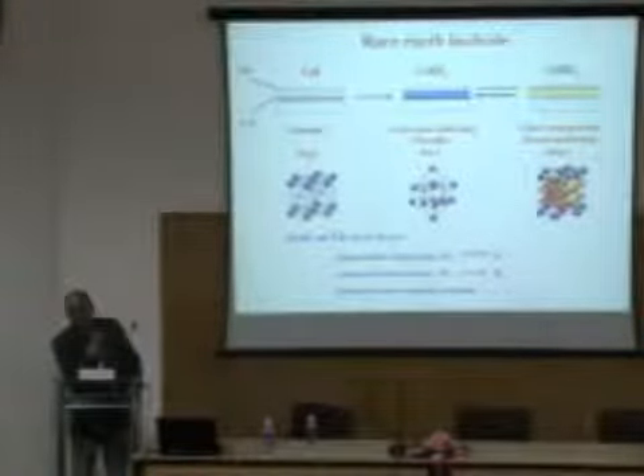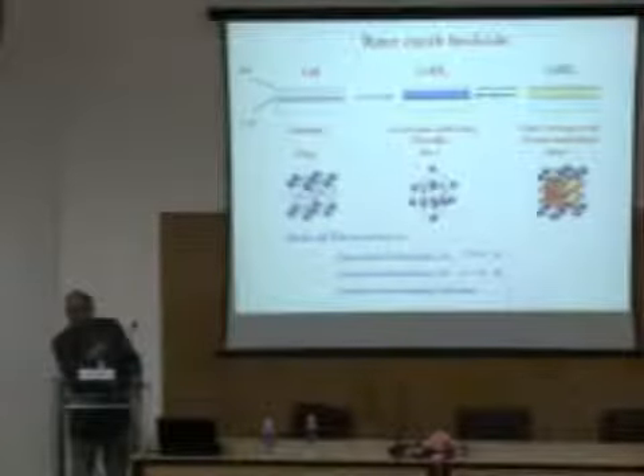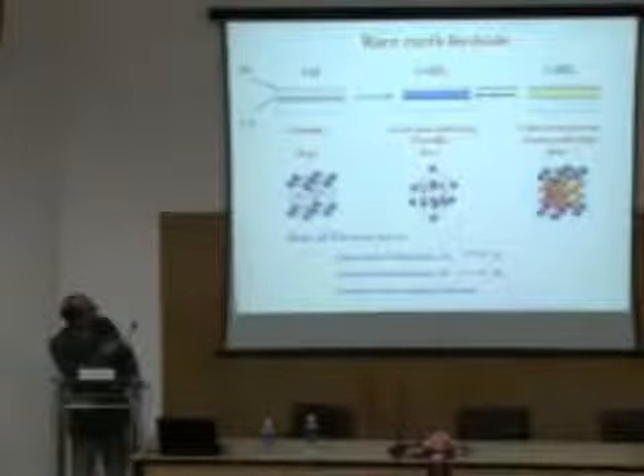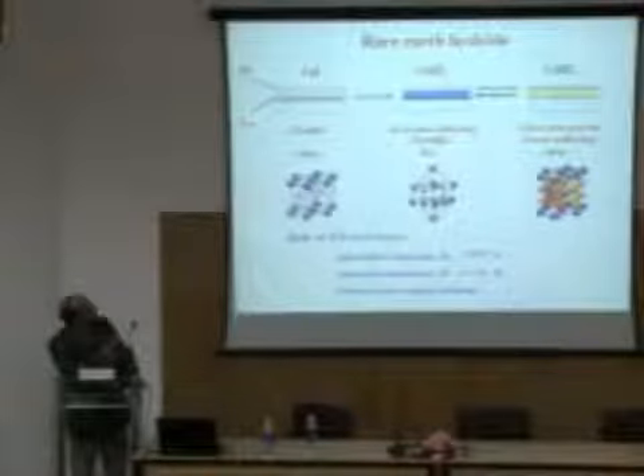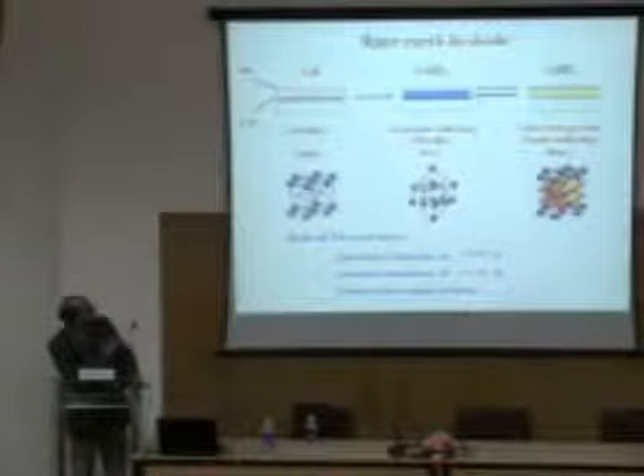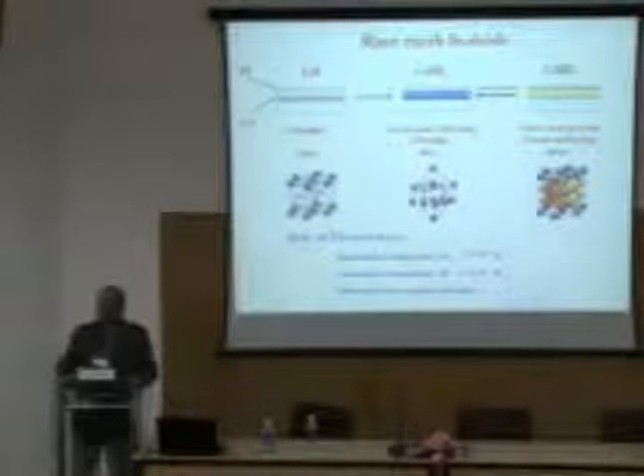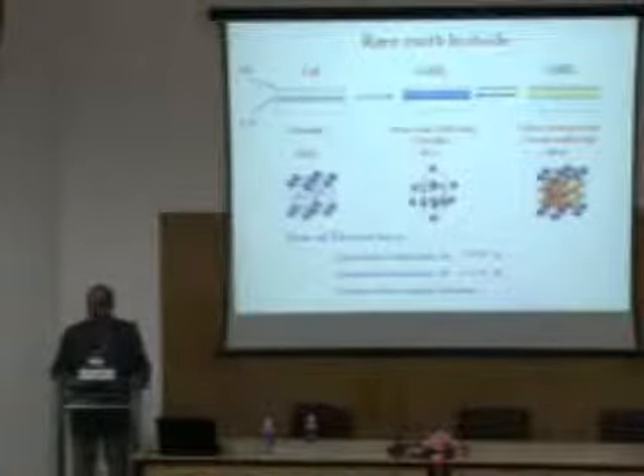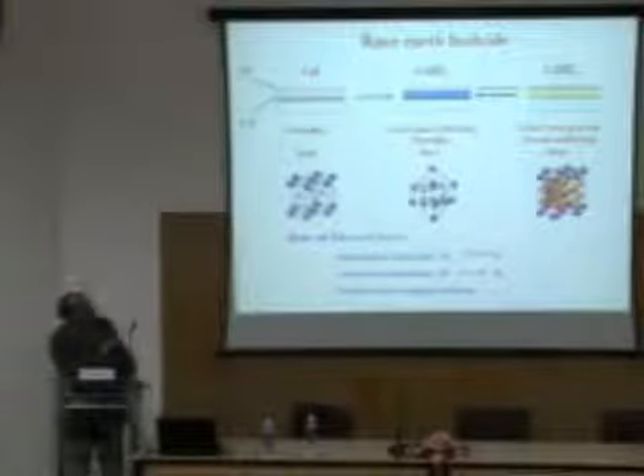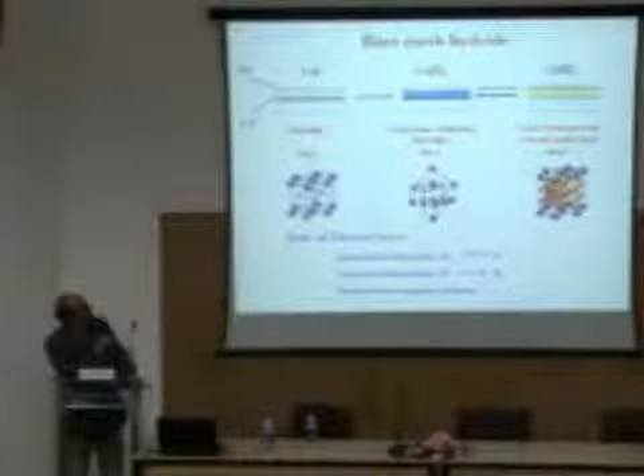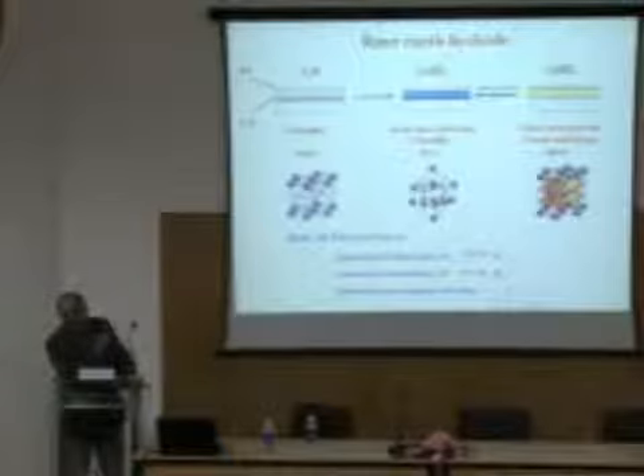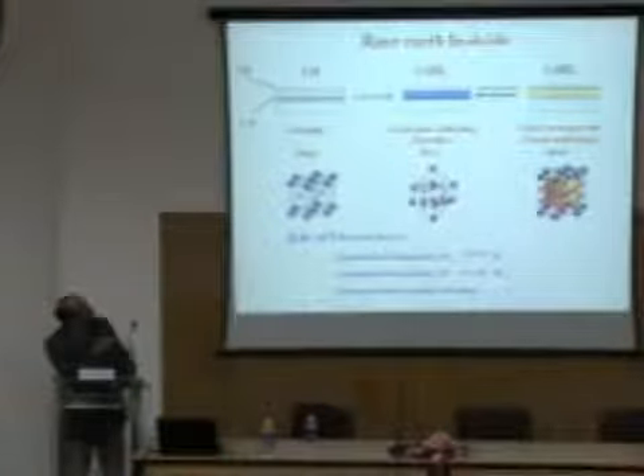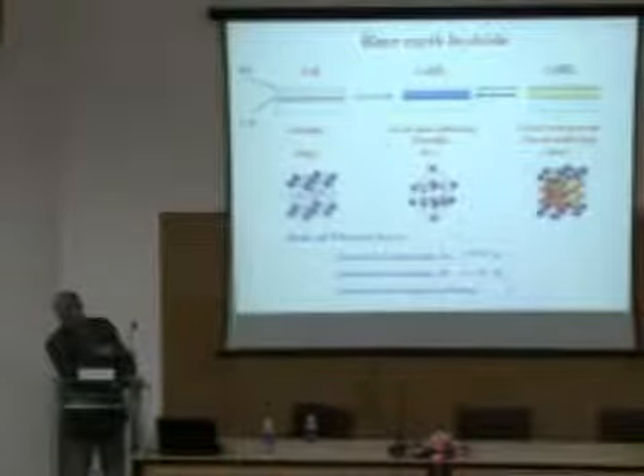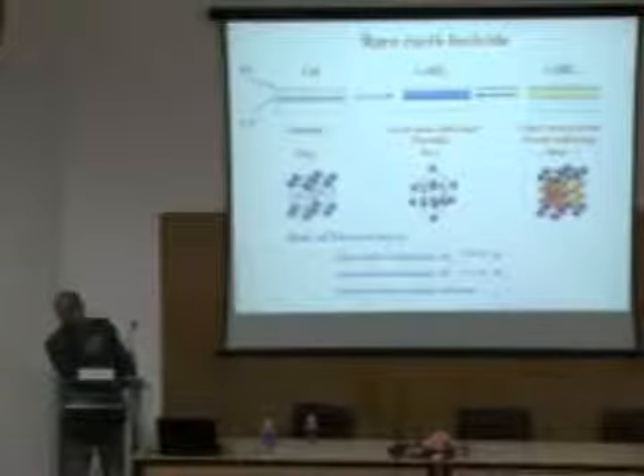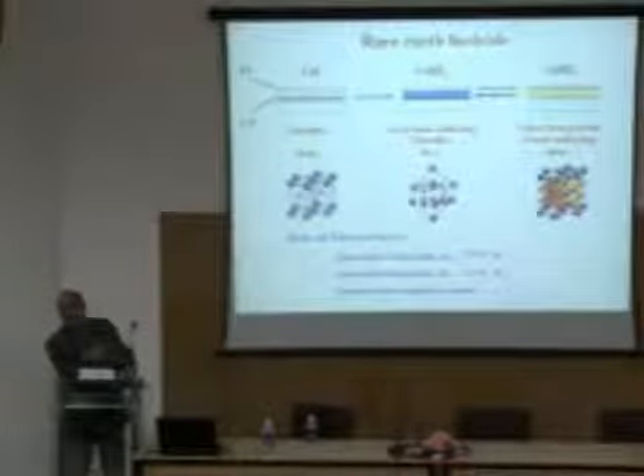We have worked with gadolinium, praseodymium, yttrium, a large number of rare earth materials, but in this talk I will be taking the example of gadolinium or praseodymium. So you have a thin film of gadolinium which is covered with a palladium overlay. When this structure interacts with hydrogen, gadolinium, which is in the metallic state, goes to what is called the gadolinium dihydride phase. Each atom of gadolinium gets attached to 2 atoms of hydrogen.